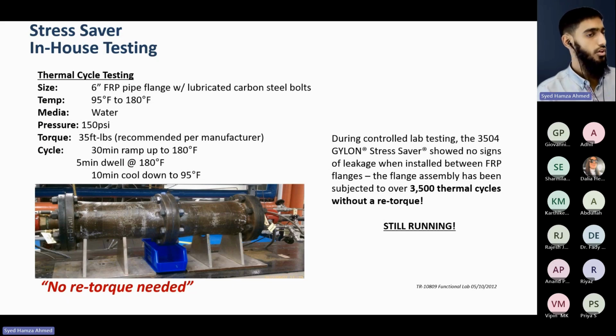And it went through cycles like a 30-minute ramp up of temperature from 95 degrees Fahrenheit up to 180 degrees Fahrenheit, then a 5-minute dwell at that 180 degrees Fahrenheit temperature, then a cool down period of 10 minutes down to 95 degrees Fahrenheit. So this controlled testing of this model showed no signs of leakage when installed between FRP flanges. The flange assembly has been subjected to over 3,500 thermal cycles without a need for any retorque.